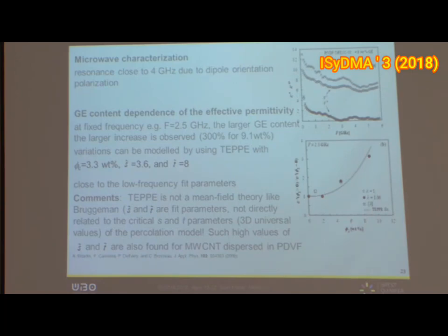Here's a caveat: TEPPE is not a mean field theory, which relies on first principles of physics. So you have to be careful when you look at this very good fit, because the interpretation of the percolation threshold is pretty clear, but these two parameters, S and T, differ very significantly from what we call the universal exponent of standard percolation theory. You should be careful to understand such results.